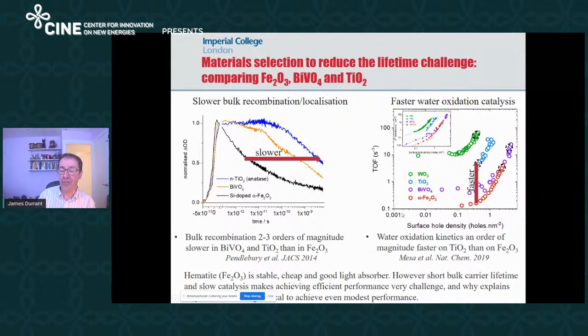versus the amount of holes on the surface. The point here is that these numbers are timescales of the order of 1 or 10 per second, so the order of a second or 100 milliseconds for reaction times. You can see the reaction times vary with hole density. I'll come to that later. And that, of course, is an illustration of a kinetic challenge between picoseconds to nanoseconds here and hundreds of milliseconds to seconds here. It's also obvious that the kinetic challenge varies between oxides.